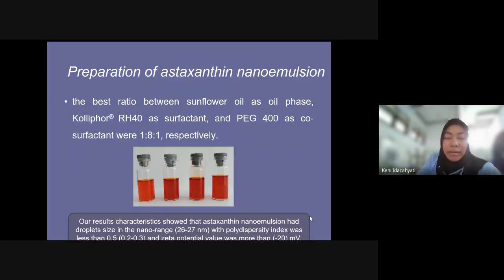The results: first, the preparation of astaxanthin nanoemulsion. As you can see on the slide, the ratio between sunflower oil as oil, Cremophor RH 40 as surfactant, and polyethylene glycol 400 as co-surfactant was 1 to 8 to 1 respectively. The characteristics of the nanoemulsion: the droplet size was in the nano range, 26 to 27 nanometers, with a polydispersity index of less than 0.5 and a zeta potential value of more than minus 20 millivolts.